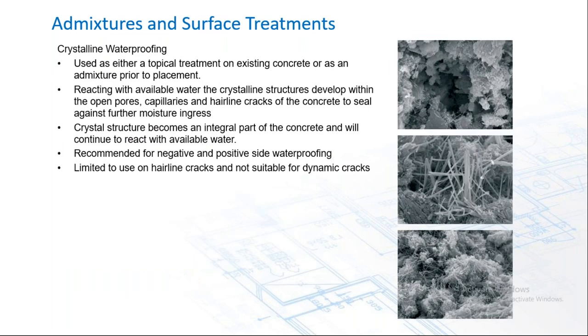So crystalline waterproofing can be employed either as an admixture or as a surface treatment. These chemicals react with the available water, and crystalline structures develop within the open pores and capillaries and hairline cracks of the concrete to seal against further moisture ingress. Understanding that concrete is full of pores and capillaries, this now creates an additional growth of these crystalline structures to prevent moisture ingress. It becomes an integral part of the concrete and will continue to react with available water. It's recommended typically for negative side or positive side waterproofing, and really limited to use on hairline cracks and not suitable for dynamic cracking.